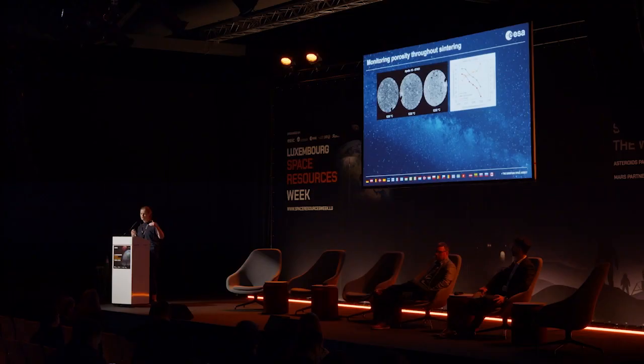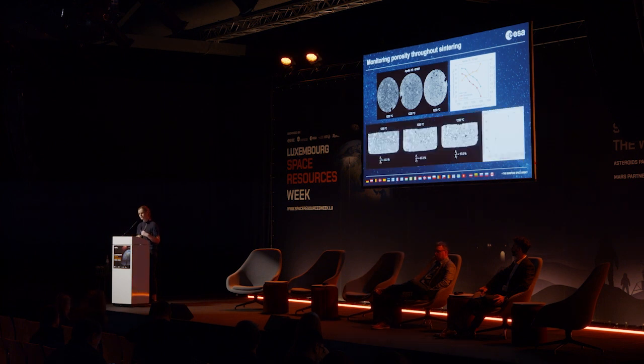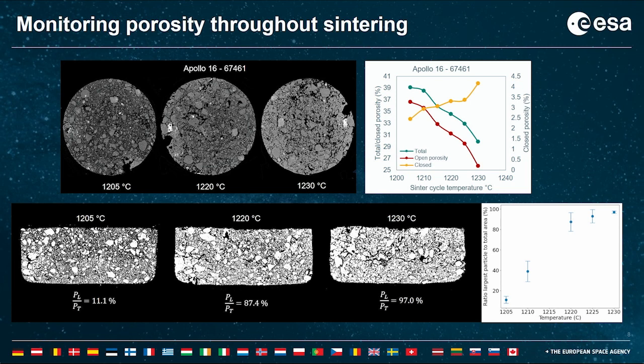So using this first data set, I wanted to look for a way to look at how sintered the material is in a more comparable way. And so to do this, I took 50 slices throughout the XCT 3D image, and from the binary image, calculated the ratio of the largest particle area to the total particle area size. So it's essentially just a metric of particle connectivity. So in the final one there, we can see that the largest particle, 97% of the particles are actually connected together.